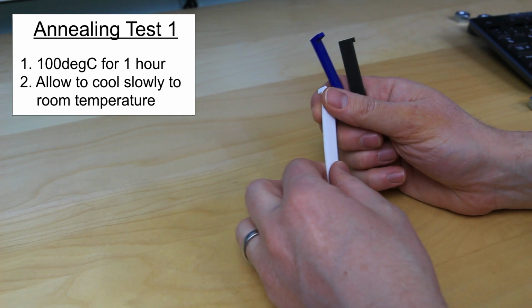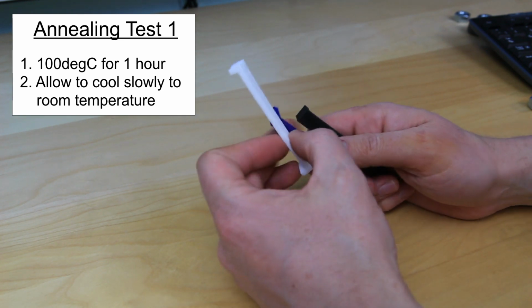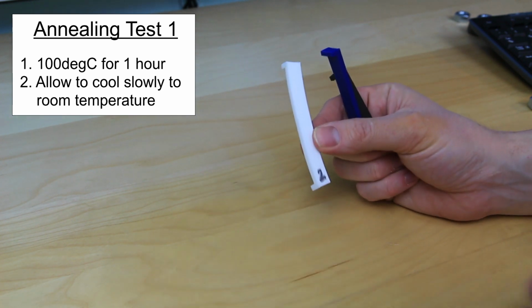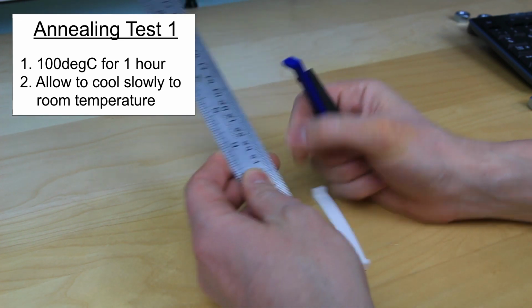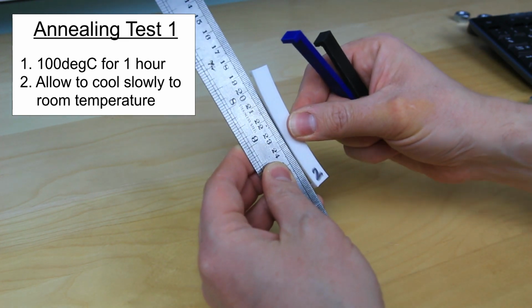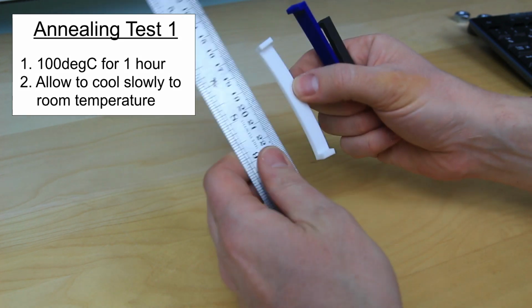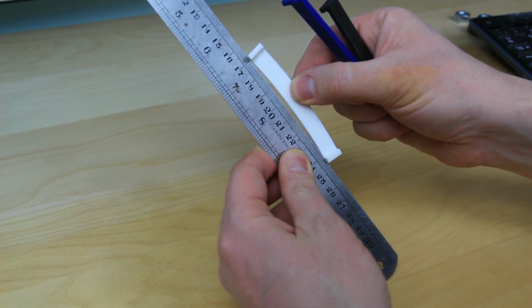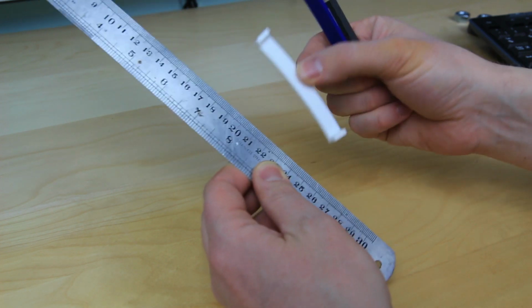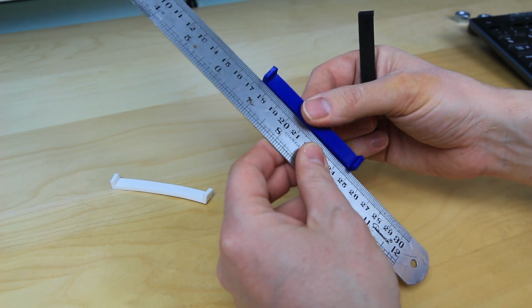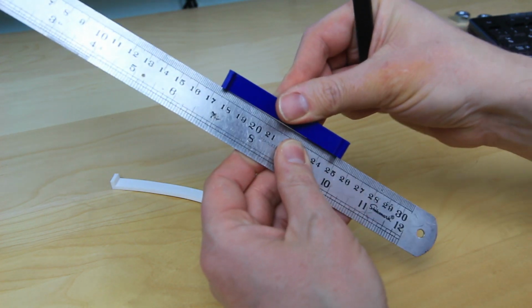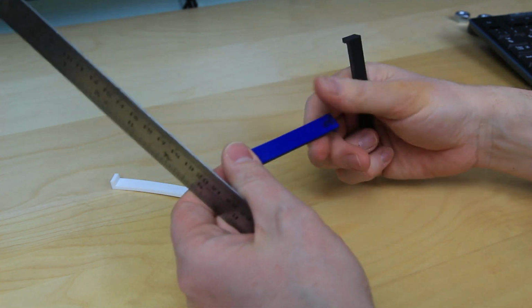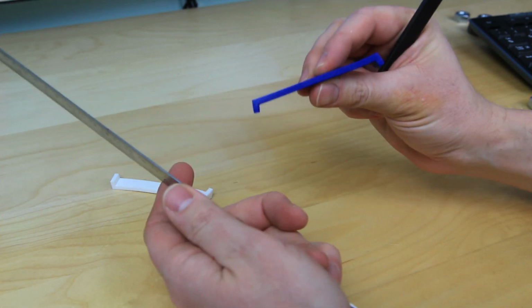So I did 2 annealing trials, one at 100 degrees for 1 hour, and these are the results. So you can see the PLA has warped fairly well, well to the point where you wouldn't be able to use it as a part anymore for its intended purpose. The PETG is still relatively straight, although there is a bit of a gap there if you can see it, but certainly it's warped enough, so again you couldn't use that for its intended purpose.